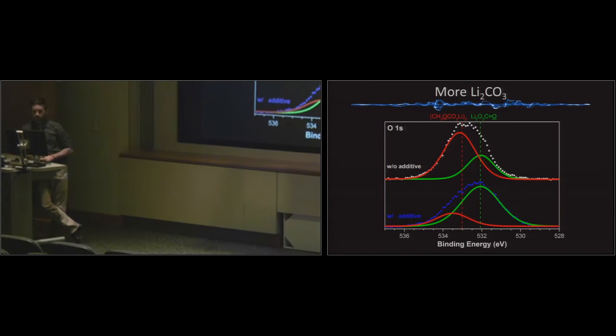And so I wanted to look and confirm that these 2 materials were actually being formed on the surface. And so to do that, we use a technique called X-ray photoelectron spectroscopy. So the two different materials show up as these sort of curves here, where again, red is bad and green is good. And so the top curve shows the system without the additive. And you can see there's a lot of the red material and not so much of the green material. But once we add the additive in, with the second curve down here, the two curves flip and there's a lot more of the green material. So this just confirms that we formed that beneficial green material on the surface.